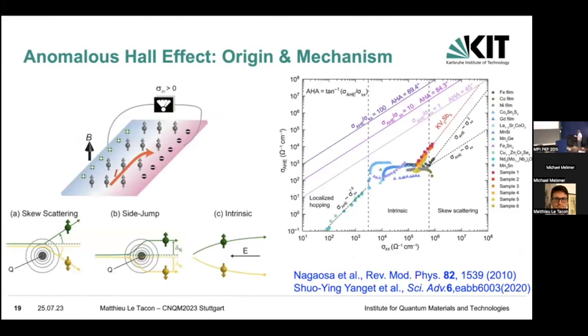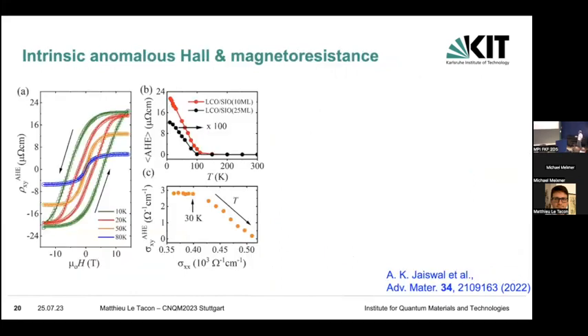So there are several origins for the anomalous Hall effect. This can be extrinsic or intrinsic. There's a way to distinguish that. We basically have to compare the longitudinal conductivity with the transverse one. And this is intrinsic when the transverse conductivity does not depend on the longitudinal one. And so this is what we've been showing here. That only occurs at low temperature, below 30 K or so. So the transverse conductivity does not depend on the longitudinal one, which tells us that this is really an intrinsic effect. And the second interesting observation is that if you increase the thickness of the strontium iridate layer, the amplitude of the effect decreases strongly. So that's really an interfacial effect.